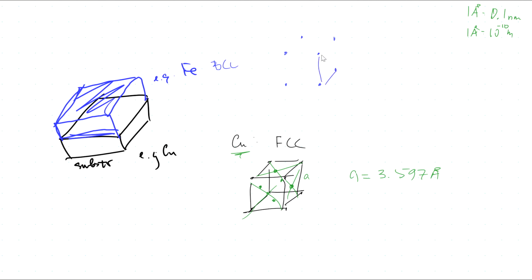So you have a cube with atoms in the vertices of the cube, but if you draw the diagonals, let me use now red. If you draw the diagonal here, there would be one atom right in the middle, and atoms here, there, and there. So these are all iron atoms, but it's structured in a way. So for iron, A is equal to 2.856 angstroms.